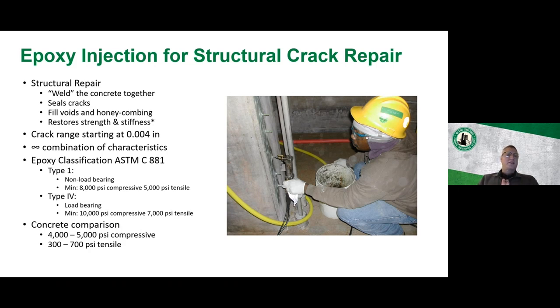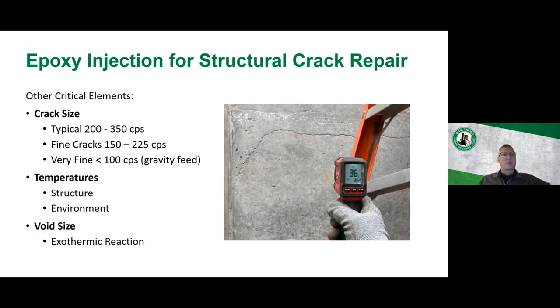And epoxy, once it bonds, has a 7,000 psi. So it grabs and it has a very high tensile strength, while concrete only has, typically I usually use about 300 on the tensile strength, which is the part where you kind of can rip it. Let's put it that way.